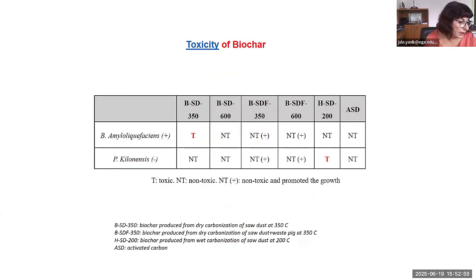Now the toxicity. Depending on the biochar type and also the bacteria type, we see some differences. For example, sawdust biochar obtained at 350 degrees Celsius is toxic for gram-positive, but non-toxic for gram-negative bacteria. And biochar obtained from wet carbonization is non-toxic for gram-positive bacteria, but toxic for gram-negative bacteria. It's very complex. The toxicity of biochar is very complex.